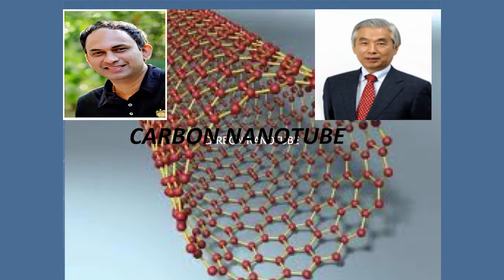We were using carbon nanotubes up until about 5-6 years ago. The discovery of graphene completely overshadowed the carbon nanotube. It's a very simple discovery. Theoretically, it was possible to take a carbon nanotube, rip it apart, and lay it on a flat table. You basically end up with graphene. When I visited the laboratory of Sir Konstantin Novoselov and Andre Geim at the University of Manchester, approximately 10 years ago, I came back not very impressed. Much earlier to that,